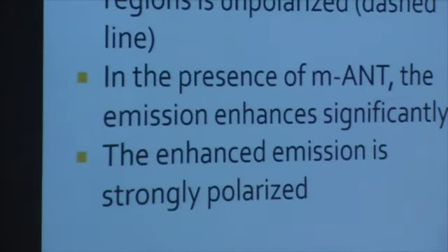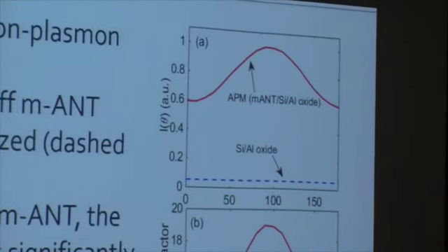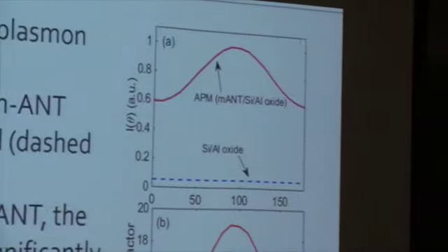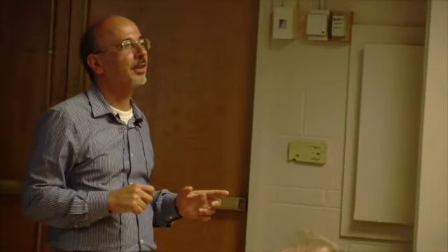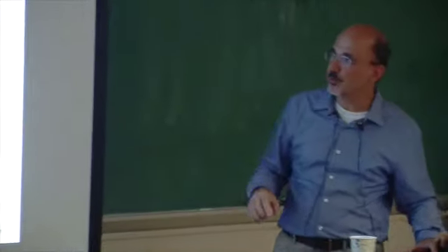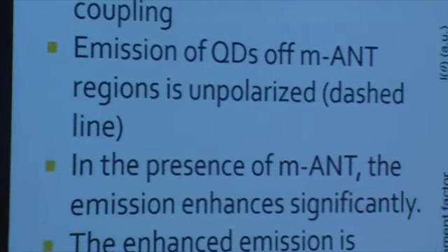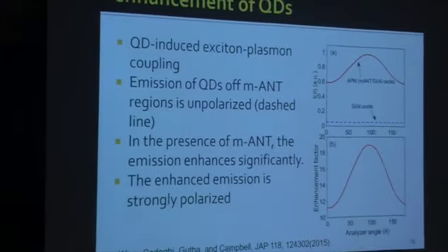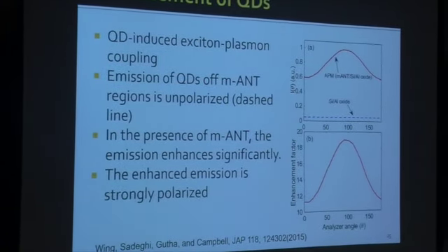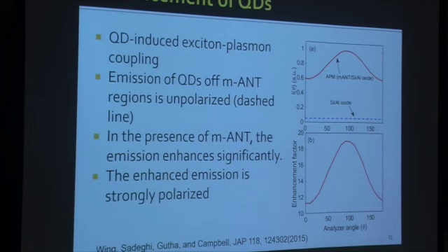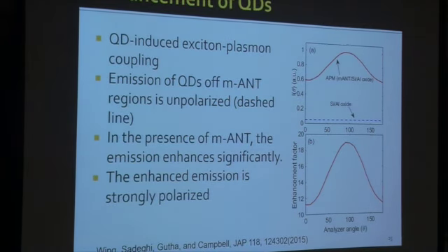And this is the first thing that you see: wow, emission is much, much more. But the more interesting part of it is that the emission is much more only along one particular axis. And that axis is the same axis as the y-axis. Remember that I mentioned y? So most of the light that is coming out is polarized along that particular axis, and the degree of polarization is immense.